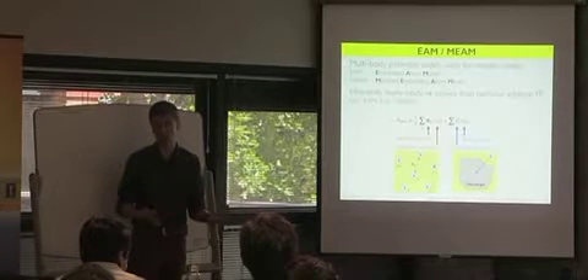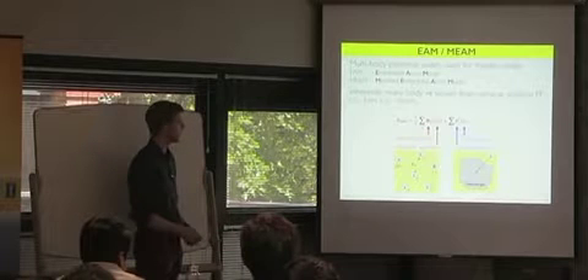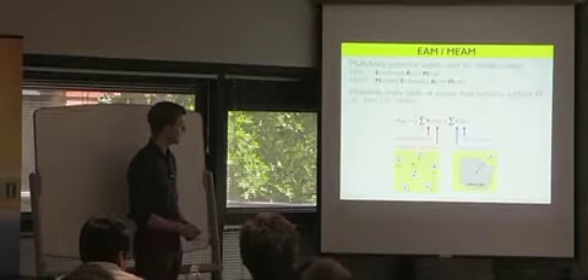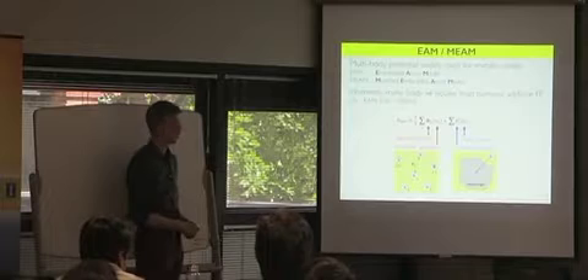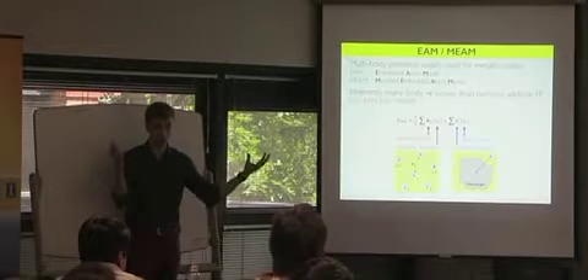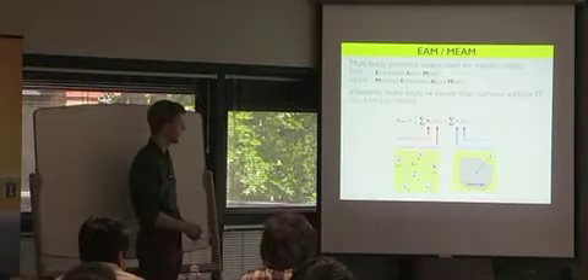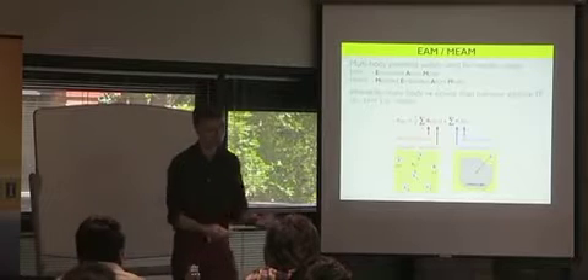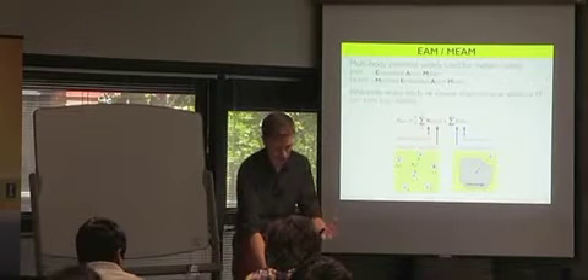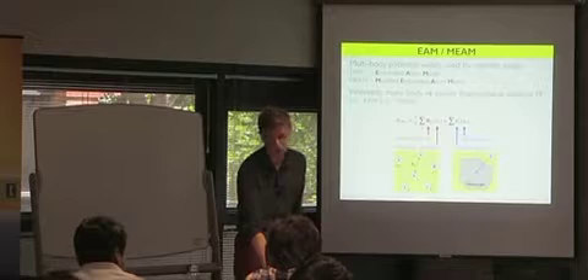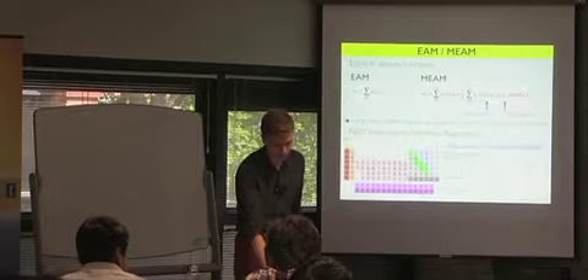It turns out pairwise is not good enough for most metals. And because of this term here, EAM is typically 2 times slower than Lennard-Jones, which is purely pairwise additive, and MEAM, which I'll show you in the next slide, is about 3 to 5 times slower. And so we do take a performance hit because of this. But you really need to do this extra multi-body thing in order to get reasonable answers.